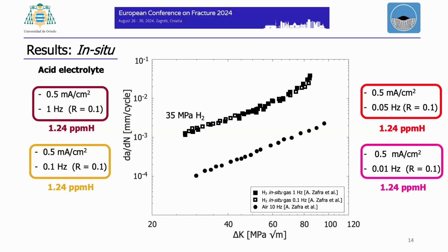Let's start with the dark red, let's say. The result was this. So for 1 hertz, we have embrittlement at the beginning of the test, but during the test, the growth rate is constant. And at the end of the test, the behavior is the same as for the air test. We decrease it to 0.1. This is the curve that we already showed you in the last slide.